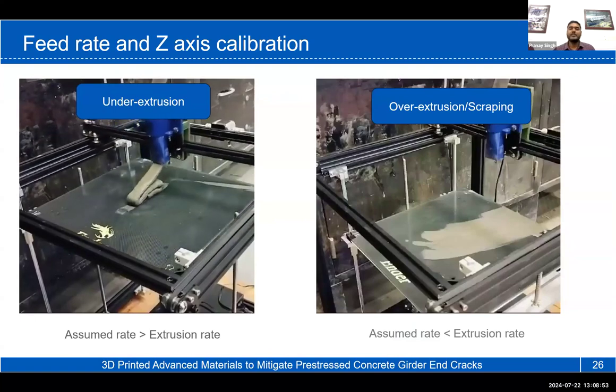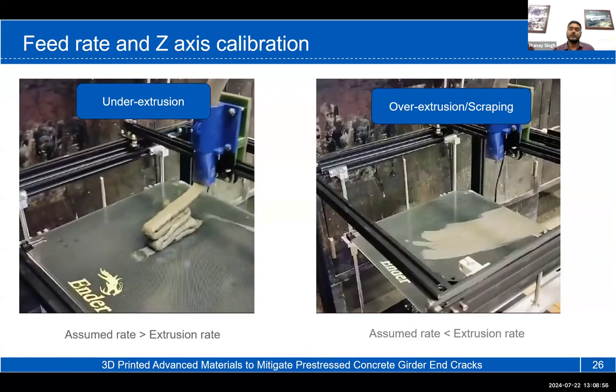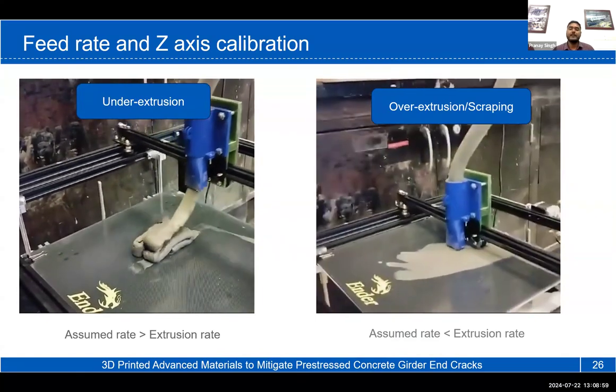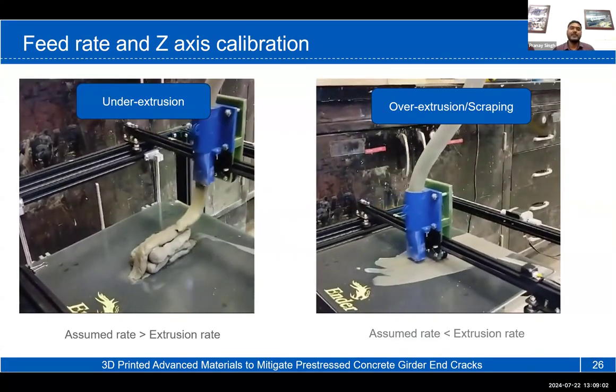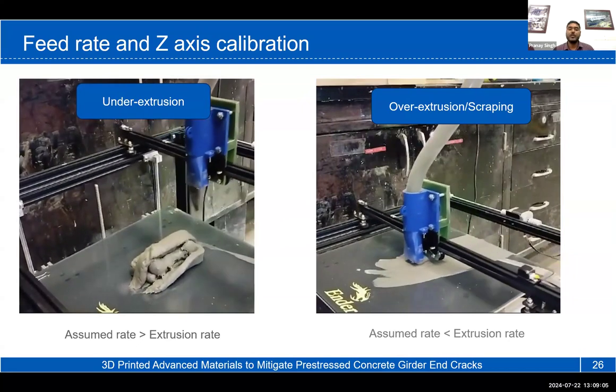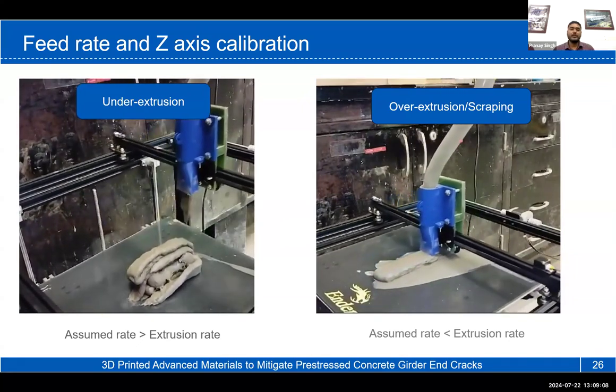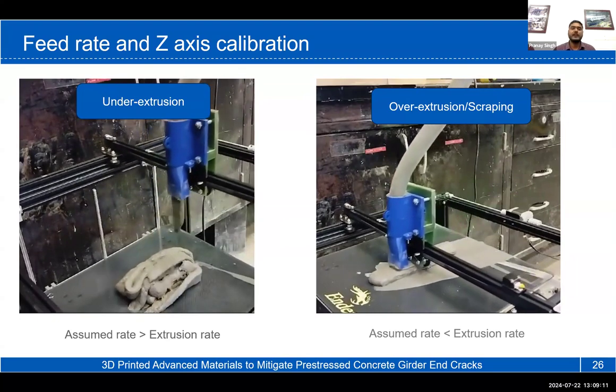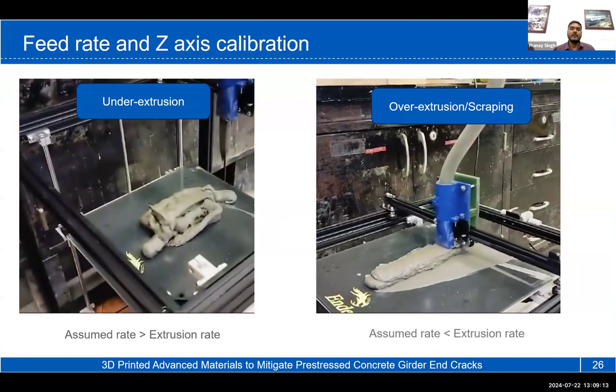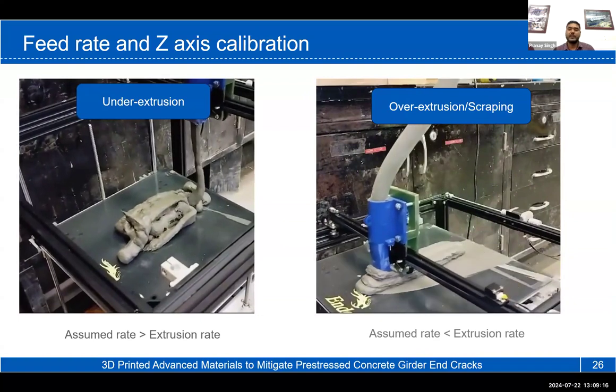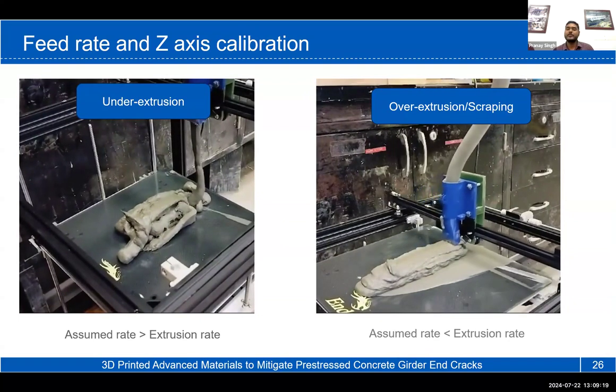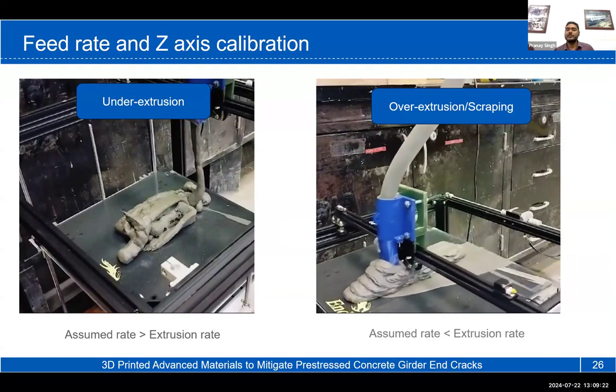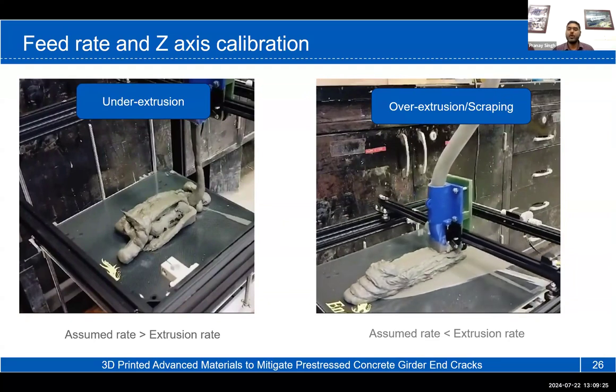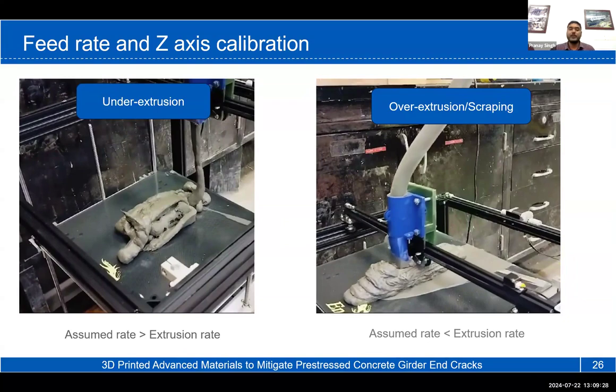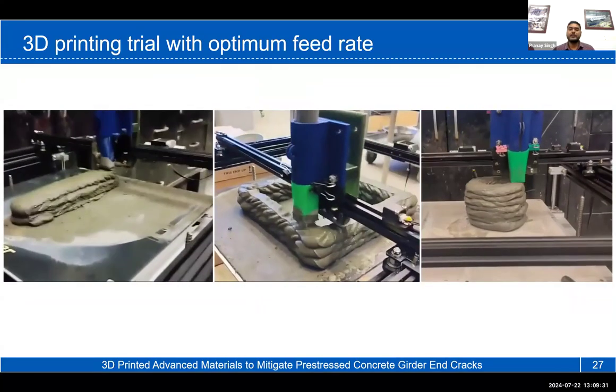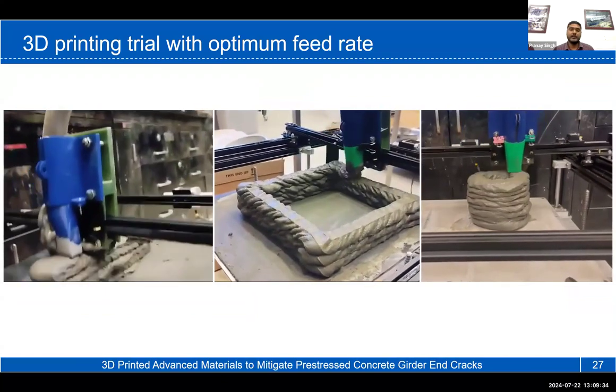One of the findings from the initial 3D printing trials is that the mix that we developed requires some initial calibration for the feed rate, that is, the speed of the nozzle and the motion in the Z direction. What you are seeing here on the left is under extrusion, where we assumed our extrusion rate to be higher than the actual extrusion rate. On the right, you can see over extrusion, where our assumed rate is less than the extrusion rate, causing some kind of scraping. Once we optimize this for a particular mix, we get this kind of 3D printing, which is good in itself.